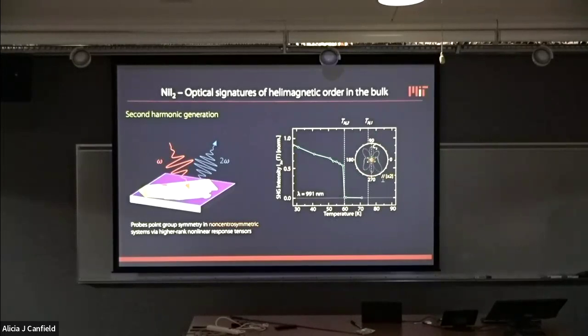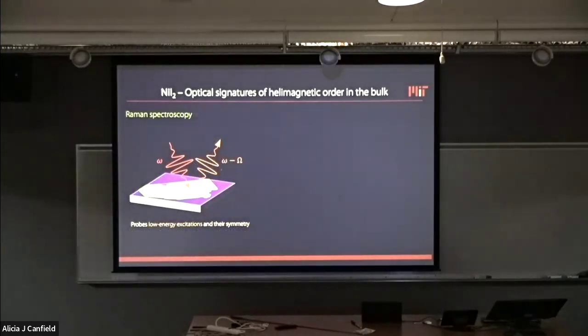Why don't you see domains? We do see domains. But then shouldn't you see the three copies of the C2 and essentially recover the C3 symmetry? We do, if you look at different spots on the sample, we see the pattern. Yeah, we do have domain mapping data. This is a local probe. It probes a lateral area of, let's say, a couple of microns. The domains are much larger. So we have inversion symmetry breaking at the same transition temperature.